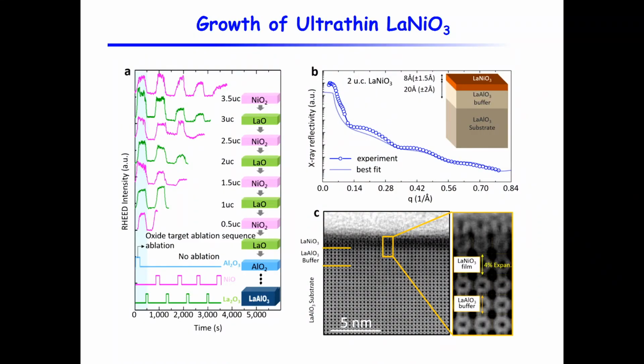Here are a bunch of RHEED intensity oscillations for half unit cell, 1 unit cell, 1.5 unit cell layers. And so we get the lanthanum aluminate buffer layer, nice, and then we start to ablate nickel oxide layers, and so on and so forth. And so the question we ask ourselves is, if you say it's 2 unit cell, how do you know it's 2 unit cell, right? So we did the X-ray reflection measurement at a synchrotron source at Brookhaven, and we fit it, and the fitting result agrees well with what we designed it to be.